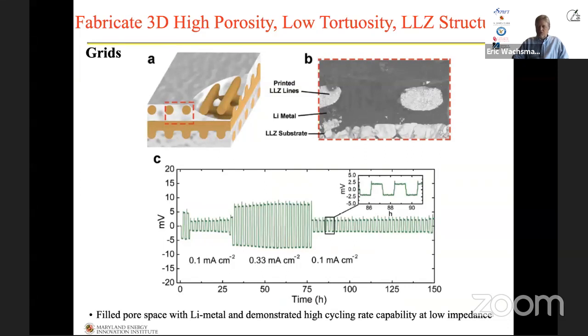And there's a blow up on there. You can see the square wave as these symmetric cells cycle lithium back and forth between the two sides. And we're literally cycling tens of microns of lithium metal at room temperature on every cycle. So it's a lot of lithium if you really think about it. They can cycle back and forth because of the high conductivity of these garnet materials. And moreover, the impedance of these things is very low, again, because of the high conductivity of the material, but also because its extended three-dimensional structure allows for high surface area.